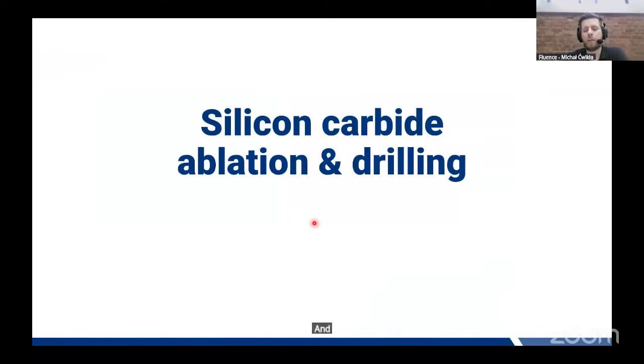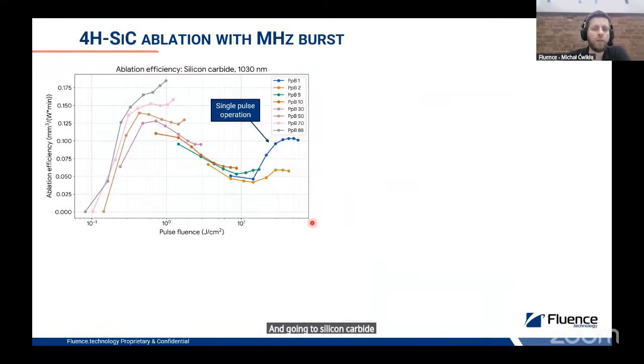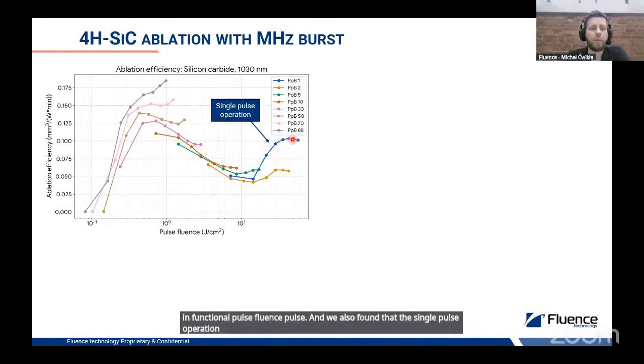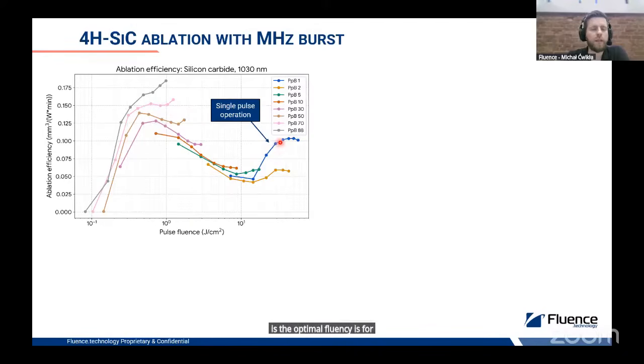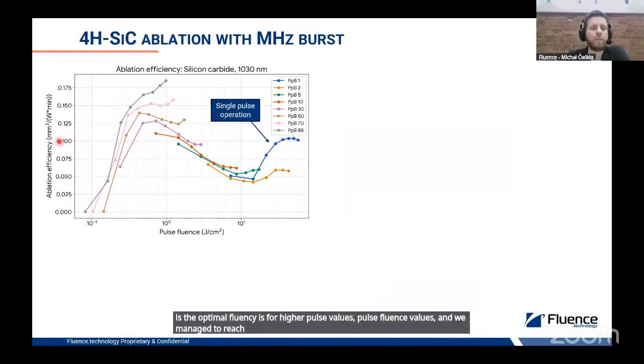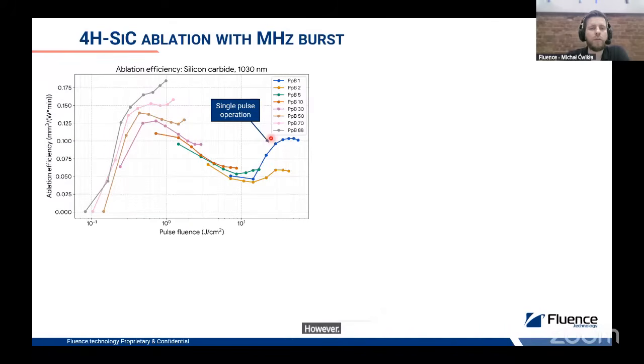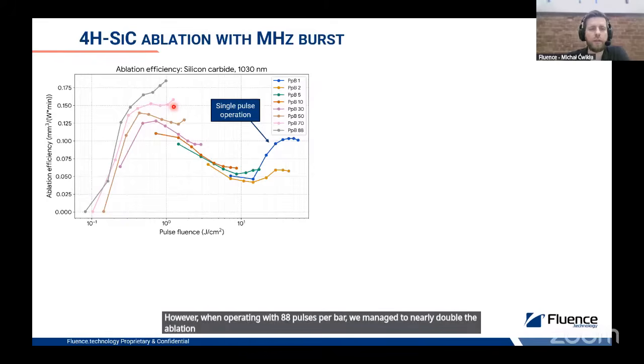And going to silicon carbide. We also did fundamental studies here concerning ablation efficiency versus pulse fluence. We found that for single pulse operation, the optimal fluence is at higher pulse fluence values, and we managed to reach up to 0.1. However, when operating with 88 pulses per burst, we managed to nearly double the maximum ablation efficiency.